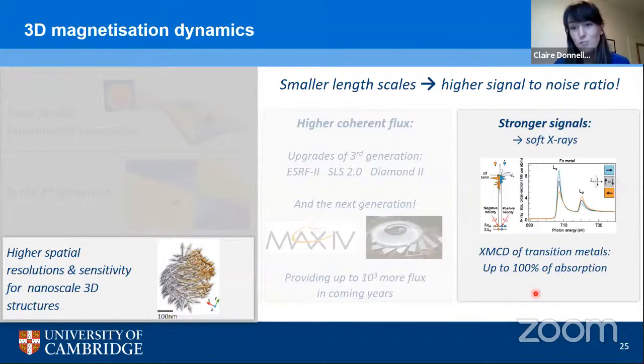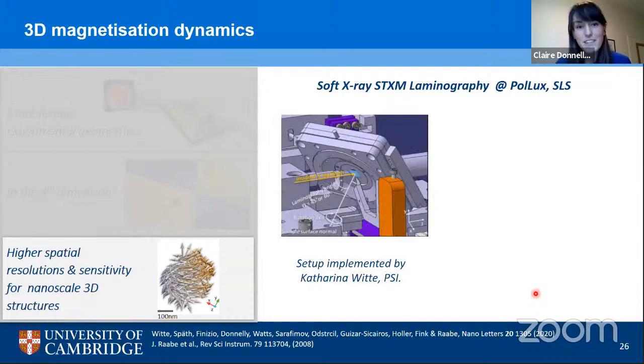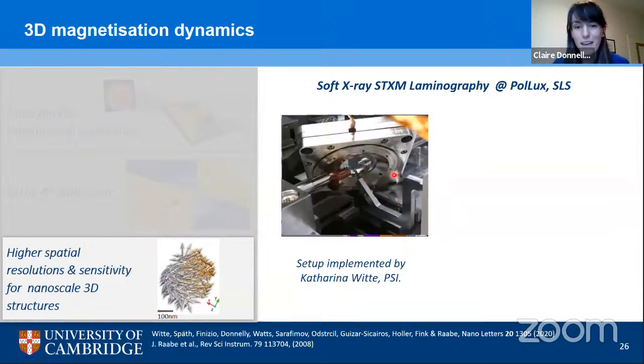choose to make use of these stronger signals by implementing magnetic laminography at the Pollux beamline at the Swiss Light Source. So if we look, first of all, at the laminography stage, and this was implemented by Katharina Witte, who's a postdoc at the beamline, you can see when we're dealing with soft X-rays, everything's in a vacuum, and with the optics, everything's quite tight. But they've done a really good job of implementing this stage for laminography, meaning that we can perform this first demonstration of magnetic laminography.